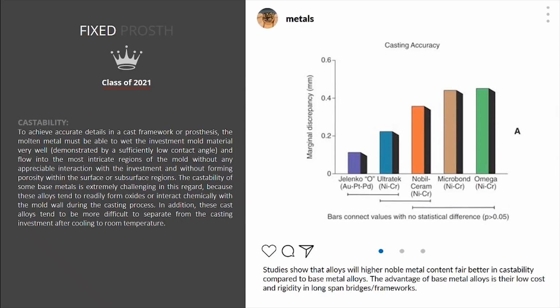So this is just a different type of study that they did, where they cast a bunch of different crowns with the various metals, and they were measuring the marginal discrepancy after casting. So these are casting accuracies. On the lower end, these are going to be your high noble metals. You can see that these are gold and platinum, palladium containing. And as you go to the higher marginal discrepancy levels, you can see that these are base metals.